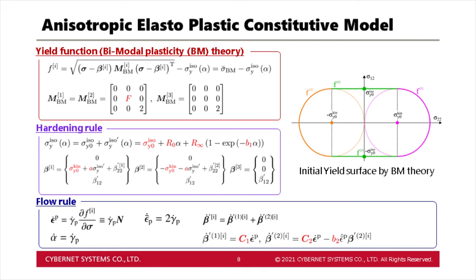When shear stress is dominant, the yield function shown in green is used. If normal stress is dominant, other yield functions are used. They are circular arcs symmetrical on the tensile and compressive sides. The hardening rule incorporates the effects of both the isotropic mode and the kinematic mode, which is expressed by the back stress. The isotropic hardening behavior is based on Voce's law, which is the same as for resin. The development of back stress is divided into the amount linked to the isotropic hardening and equivalent plastic strain component.